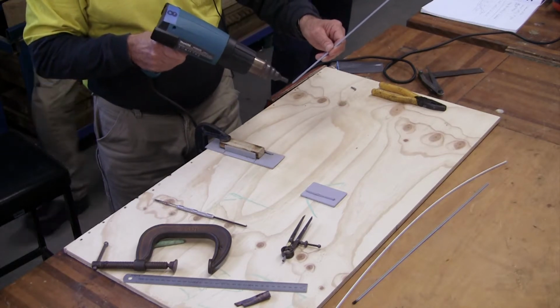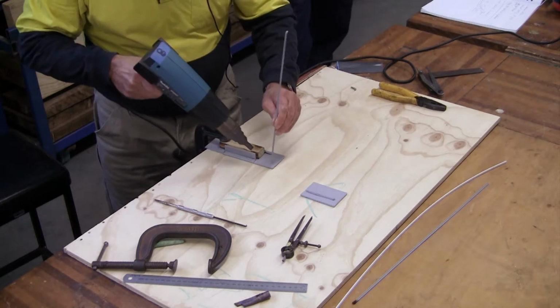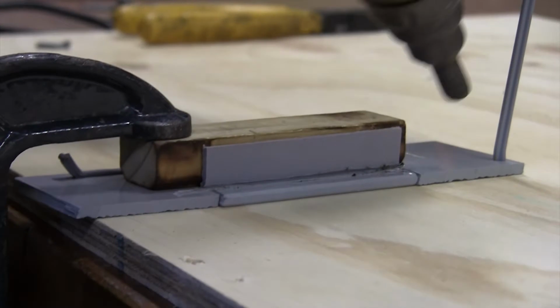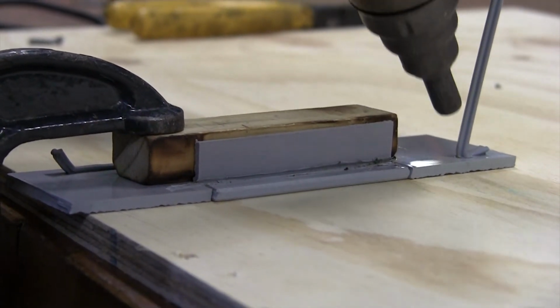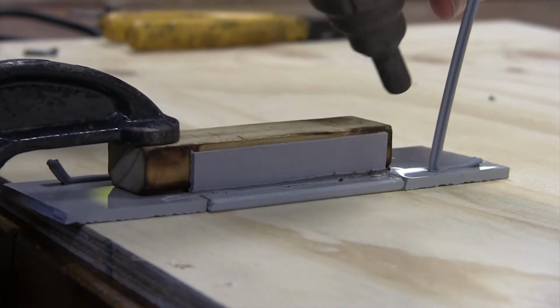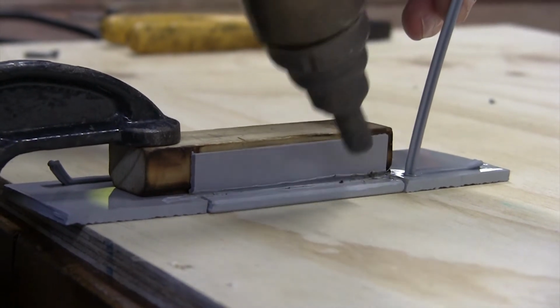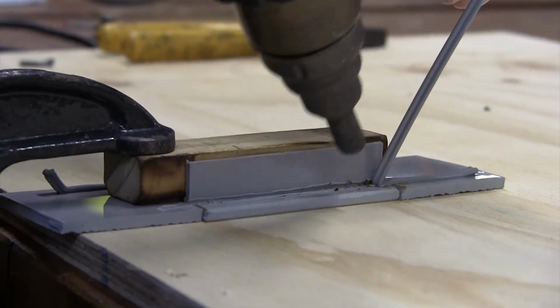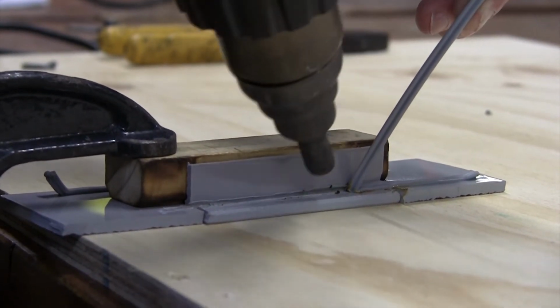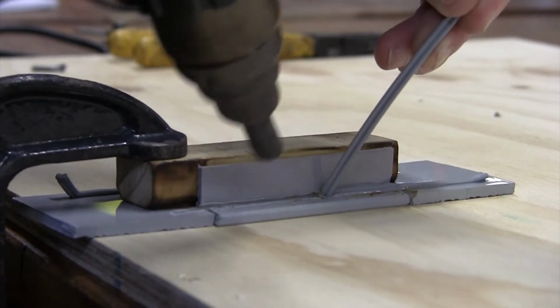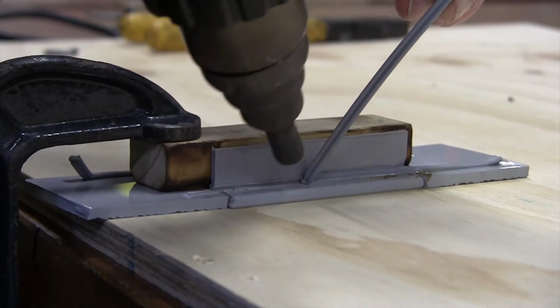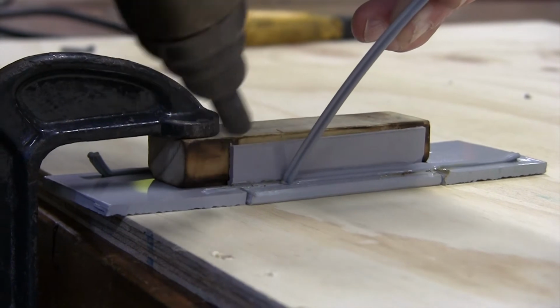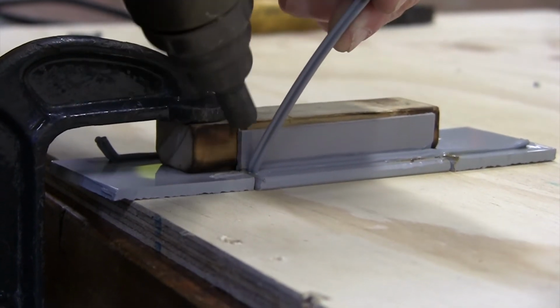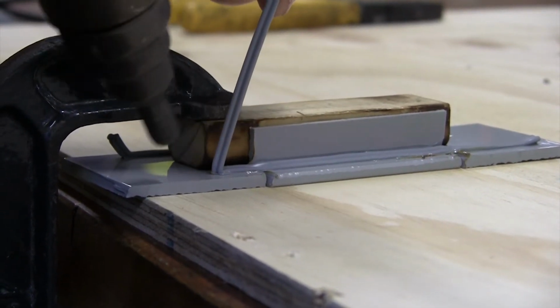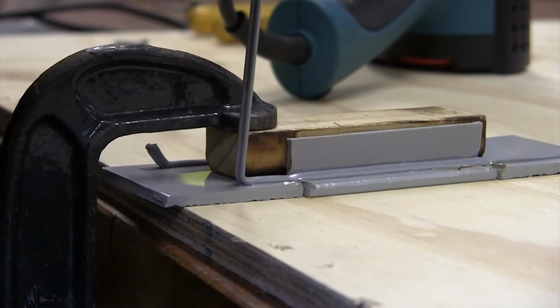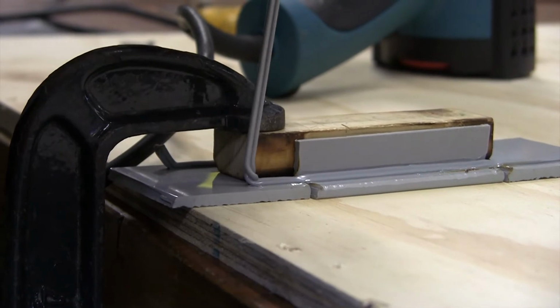Okay, preheat your tip. Ready to start welding. Pendulum motion, 60-40, downward pressure. The rod's at 90 degrees. I'm getting the bow wave. I now come over to my workpiece and the rod then goes to 45 degrees. Slight burn there, so I'll move the gun away. Take the rod off onto our sacrificial piece. Let it cool for a couple of seconds and just give it a twist.